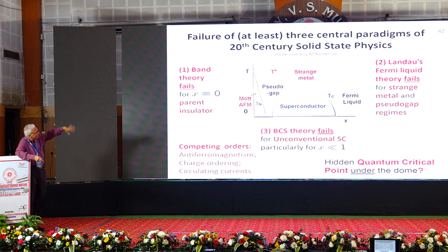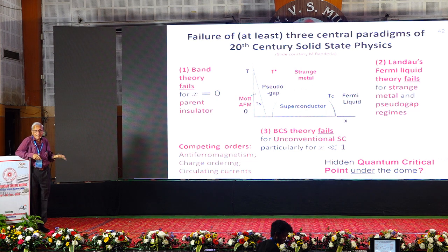So this system breaks 3 central paradigms of 20th century physics. One is band theory, which fails at x equals 0, because if you work out lanthanum copper oxide, it has one band which is half filled, so if it weren't for interactions, it would have been metallic, but it's insulating, so you know that interactions are playing a big role, like in the Hubbard model.